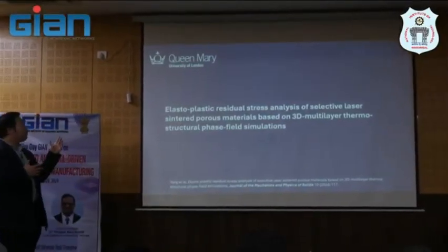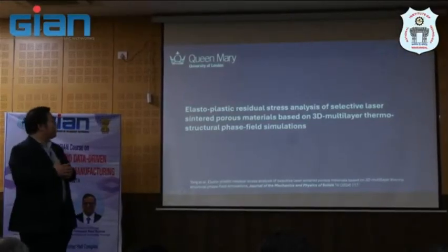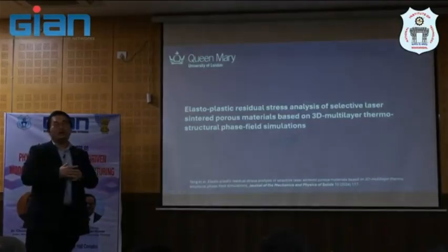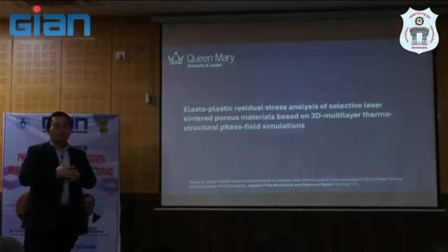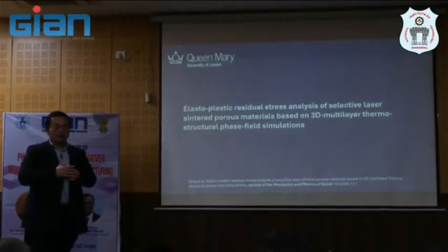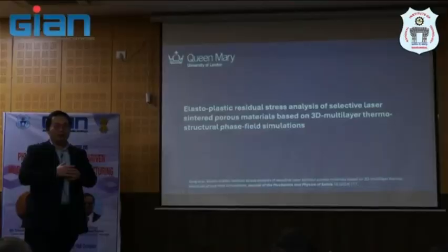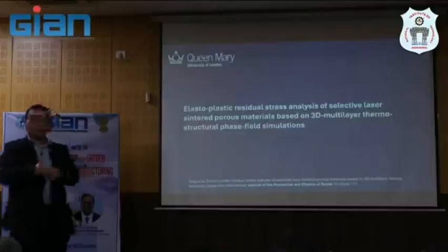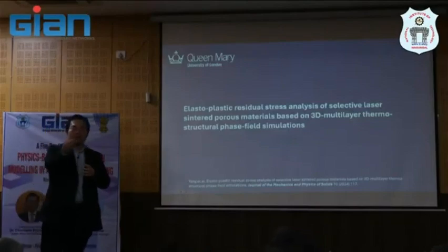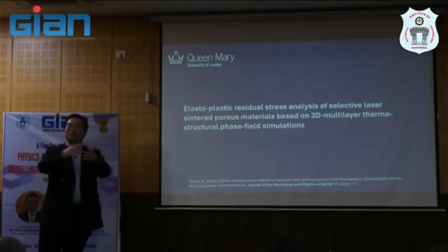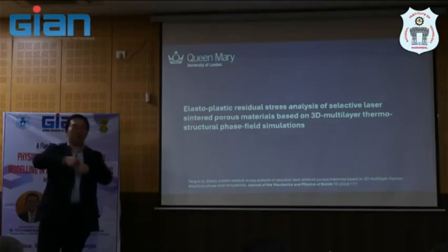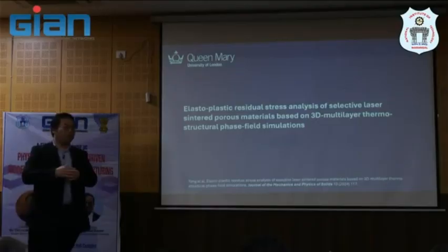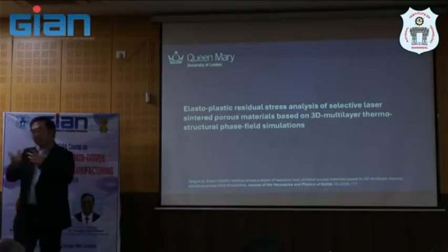And this is elasto-plastic residual stress analysis in the sintered porous material. Again, this uses laser as a sinter. So probably this is a bit different from the LPBF. The difference is that this one is a diffusion-driven process. So you use laser to just sinter the material together, so you leave behind porosity. The same processing technique you use for ceramic, but you don't need laser, right? Since ceramic uses an electric field to do sintering, or spark plasma, you use a quick electric field to basically sinter it. So they will fuse particles together.